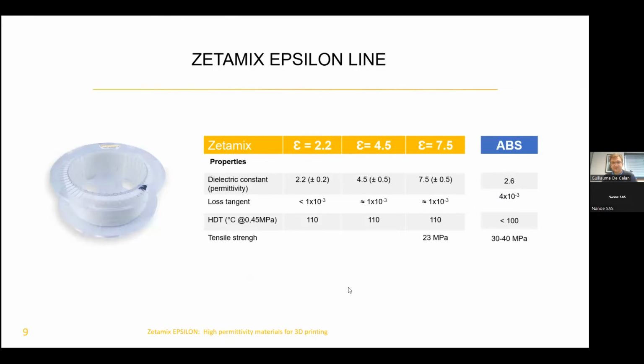So this is what we've developed with our new Zetamix Epsilon line, a line of 3 different filaments with different permittivities, ranging from 2.2 to 7.5, with very low loss in the material. Those were mainly the 2 characteristics our first customer needed: a high permittivity and a low loss. You also need 2 other things to be able to use it in most applications. We needed a relatively good temperature resistance and some, let's say, reasonable mechanical properties. This is what we have with these materials.